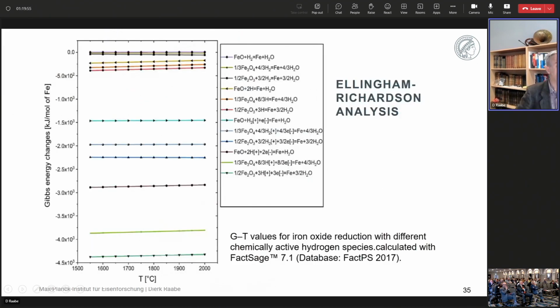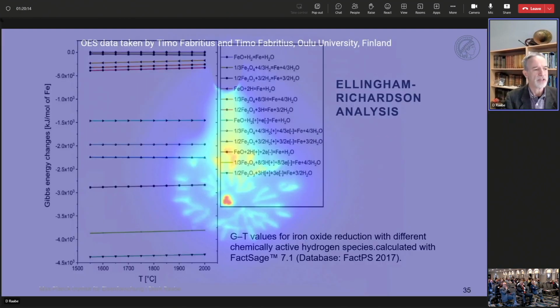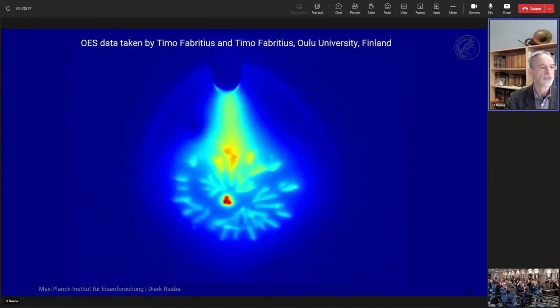In the thermodynamic analysis here in the Ellingham diagram, you can of course appreciate when you produce a plasma according to ionization energies, you go through the distribution, get the occupation of the different radicals, and then you have a much higher free energy. That means some of the reductant energy does not come from the molecule, but comes then from the ionization. What is interesting is that such equilibrium calculations are of course a little bit short-sighted, because here's a very nice OES spectroscopy done by colleagues in Finland on our reactor, where the color code shows you the poisoning of the plasma by the evaporating iron.